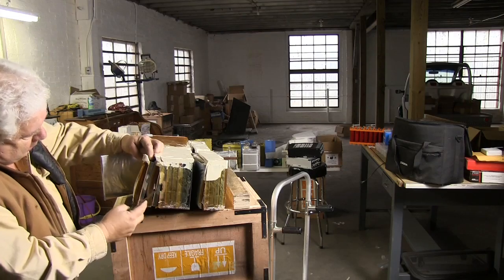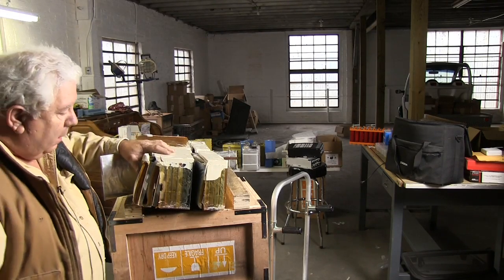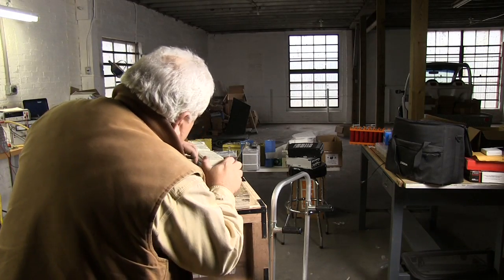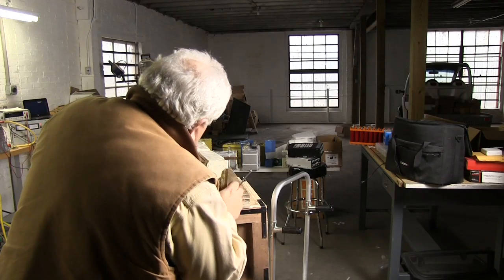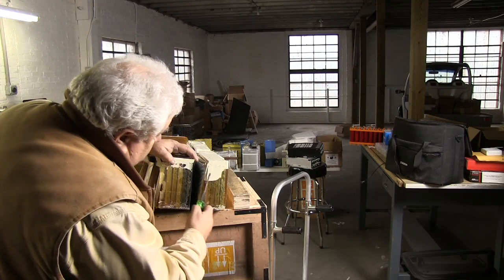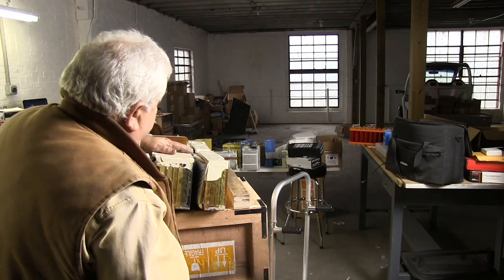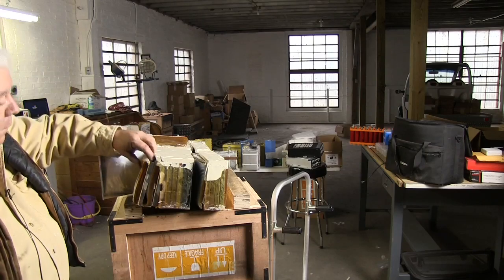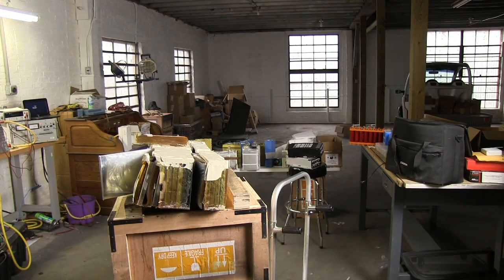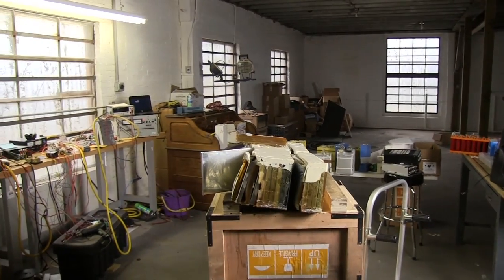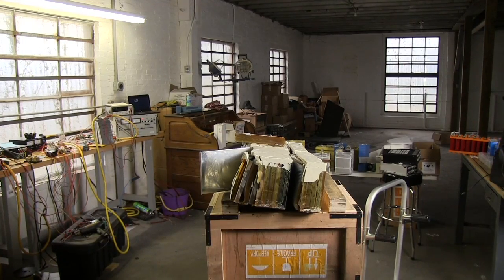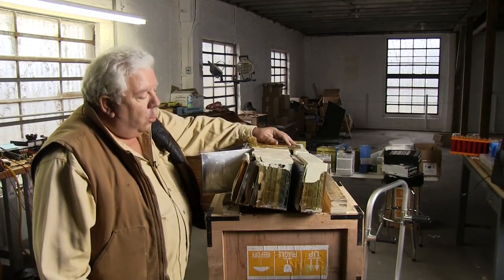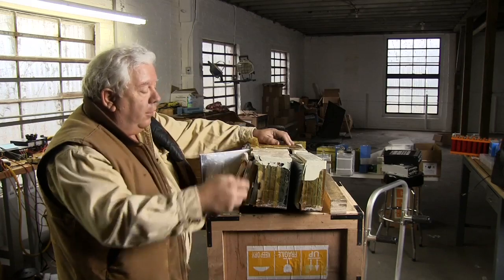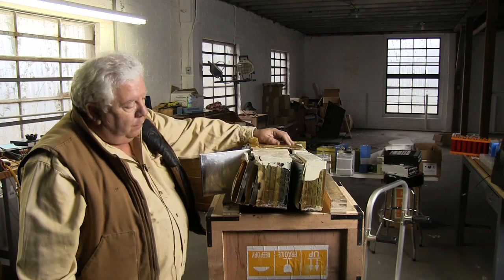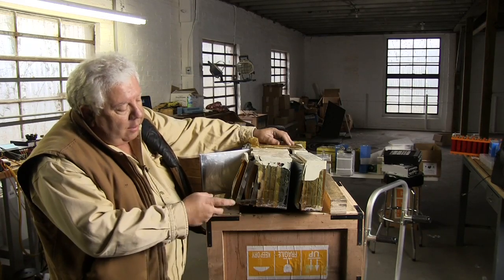And as you can see, our pouch has expanded dramatically. We actually did lose electrolyte on this adventure, and you can see here it split our pack completely lengthwise over here. What happened? You know, I'm not sure I'll ever know. We suspect the exothermic reaction of that resin pour. These cells were done 4P and 12S serial for 40 volts and 80 amp hours.